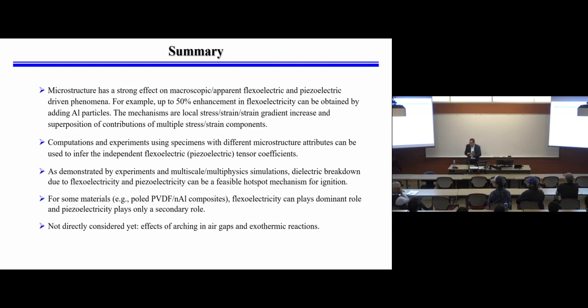Did you use phase field or finite element? This is finite element, but we do not use phase field. This is fully dynamically, physically resolved. So it's purely the full mechanical process of deformation, equilibrium, stress-strain behavior, and electrically, the full Maxwell equations that we solve. We have not used phase field.